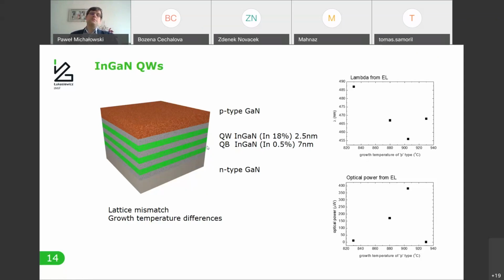And that means that usually it's assumed that the indium distribution within these quantum wells has quite a lot of fluctuations. And from electrical and optical measurements, it turned out that this growth temperature has a huge impact on the performance of such a structure. So if the temperature is low, the actual optical power is also very low and with the high wavelength. But then when we start to increase the temperature, we can see that the situation is getting better with much higher optical power. But then after some time, we can see a very sudden drop.